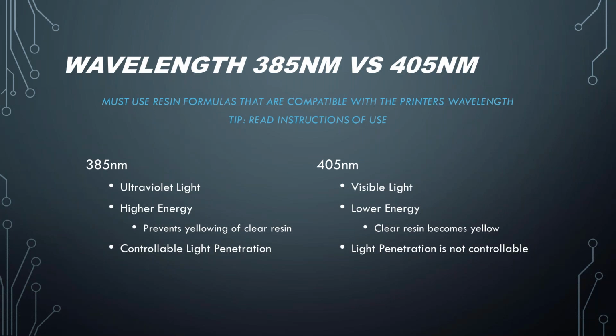The 385 nanometer light is an ultraviolet light, which is higher energy. Because it has such a higher energy, you can actually control the light penetration into the layer or into the object that we're curing. It's going to be more of a surface cure and not so much a higher depth of cure. So we can actually get a more accurate object out of a 385 nanometer spectrum printer than you can out of a 405, because we have that controllable penetration. Also, with a 385 nanometer light spectrum, you can actually print a clear resin and have it remain clear. That light spectrum prevents the yellowing of clear resins.